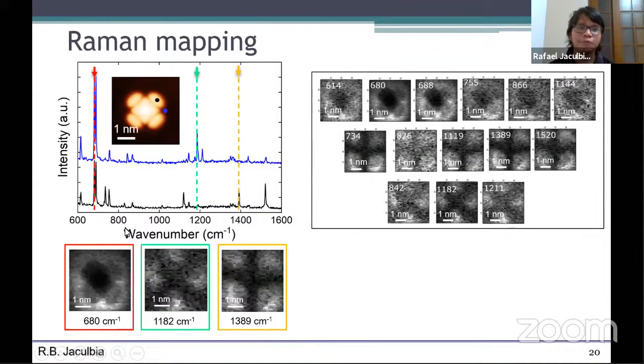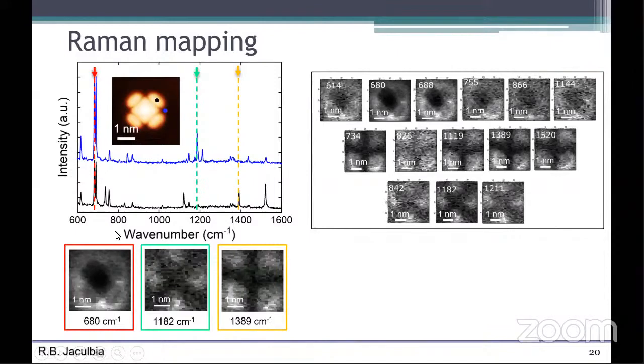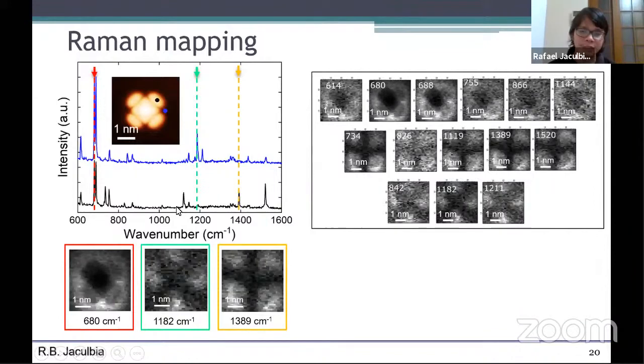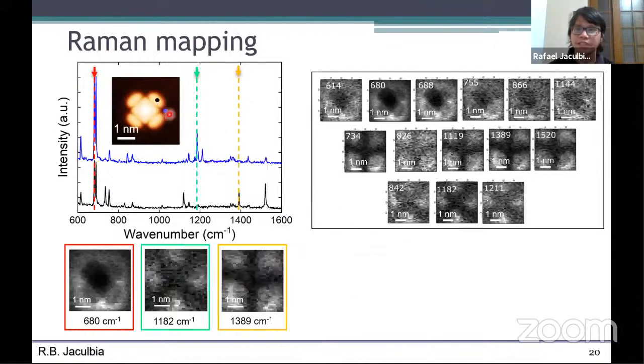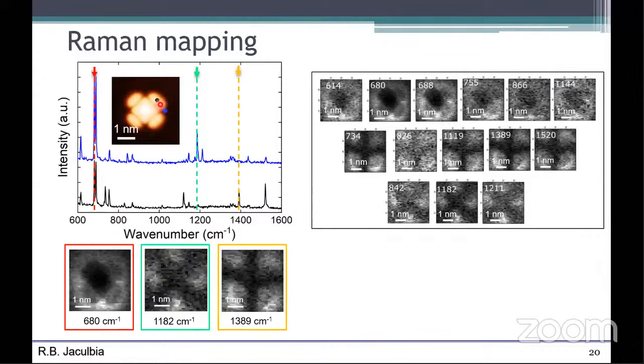I see, okay. And then post-processing, yes, you're right. And then locate that particular position. Yes po. For the corresponding Raman, okay. Of course, for the other spectrum like this po, we can very precisely place the tip at a certain point in the STM box. So especially the UHV low temperature STM is very, very stable. So there is almost no drift. So the molecule stays in this spot of the substrate for a very long time, and you can place the tip at a selected point, mainly because of the low drift. Thank you. Thank you.